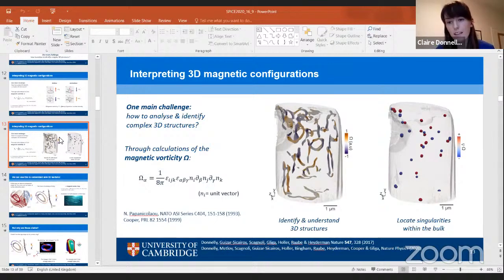In this data set, we looked at a few different samples. We get, surprisingly almost, an equal amount of positive and negative, so Bloch points and anti-Bloch points, which goes with our feeling that these are likely to have formed within the bulk during the formation of the magnetic configuration. In some other samples, we saw perhaps a slight difference from exactly 50%, but it was always roughly 50%.